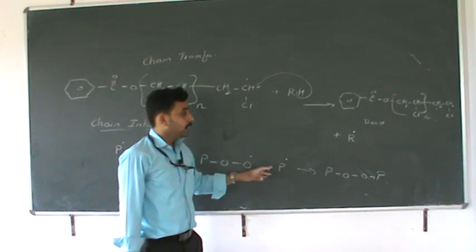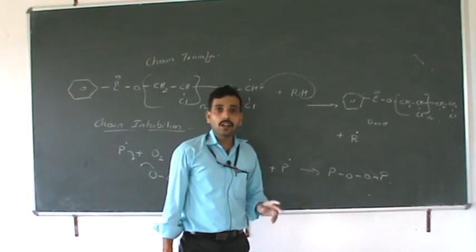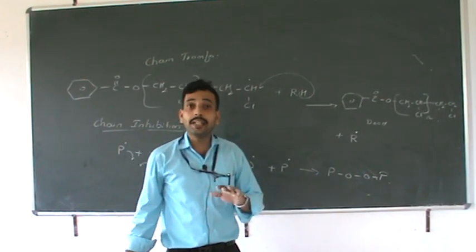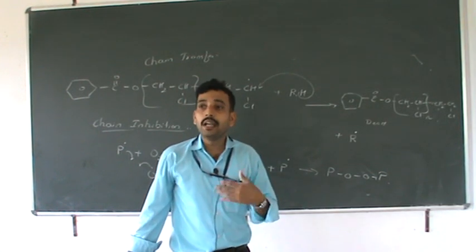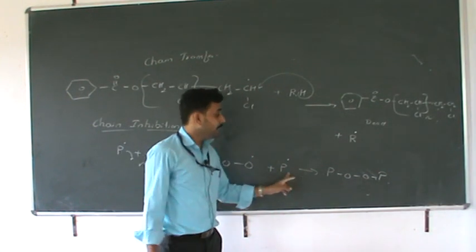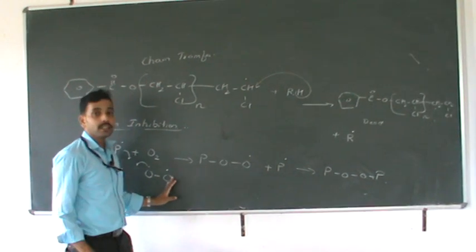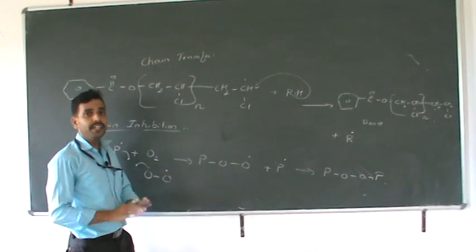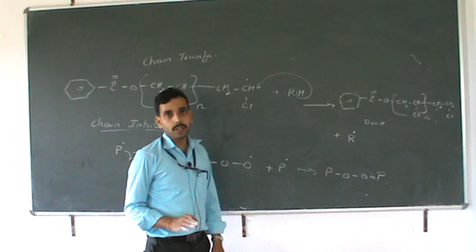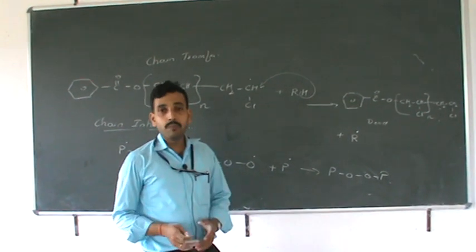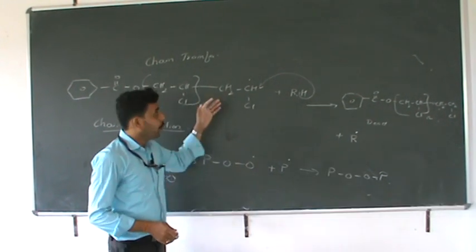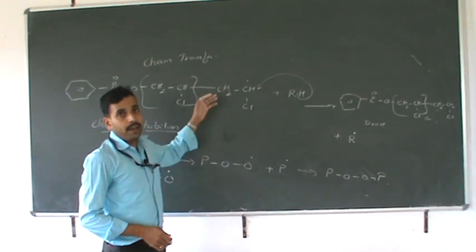So that's why free radical polymerizations are always carried out under a nitrogen atmosphere, because in atmospheric conditions, atmospheric oxygen acts as an inhibitor and will immediately arrest the growing polymer chains. So these are the more important concepts in polymerization and free radical